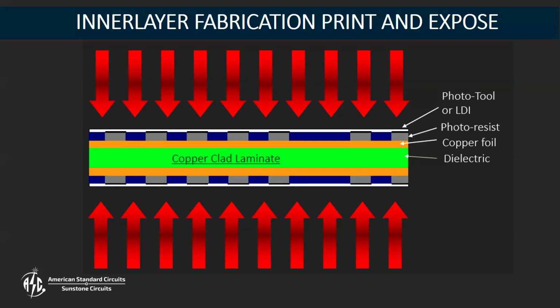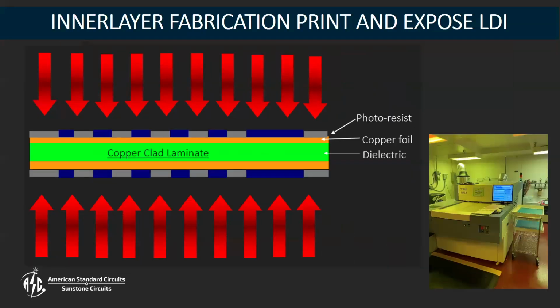So to that photoresist, we're going to run it through the imaging process, the LDI, which is basically a glorified laser jet printer. So it's going to expose the film in specific spots where we want the resist to stay long term. For an inner layer, that will be the parts that we want to keep as traces and connections on those internal layers. The parts that are going to be unexposed by that LDI, we're going to wash away, develop away, and that will act as our etch mask for that inner layer.